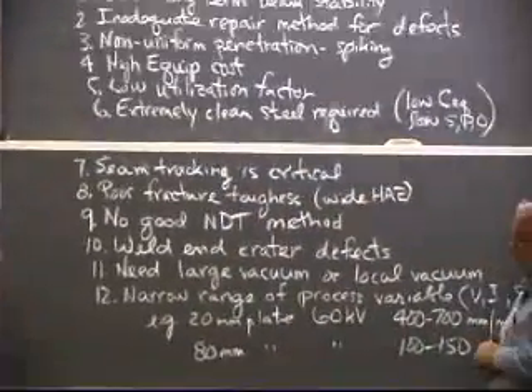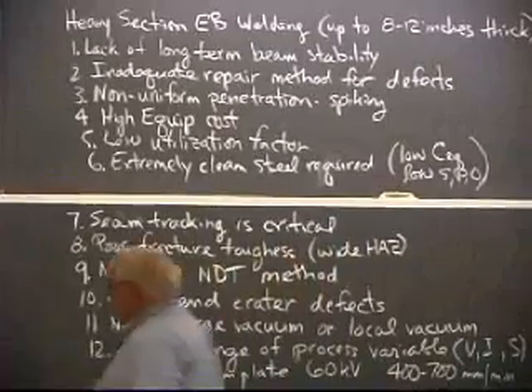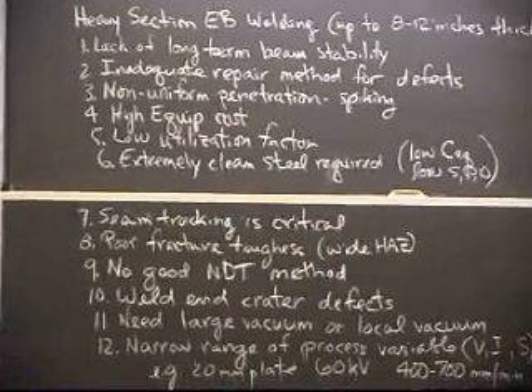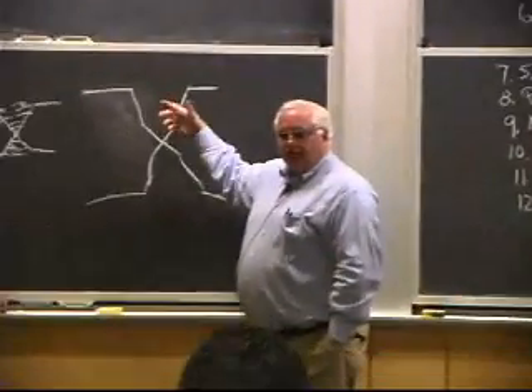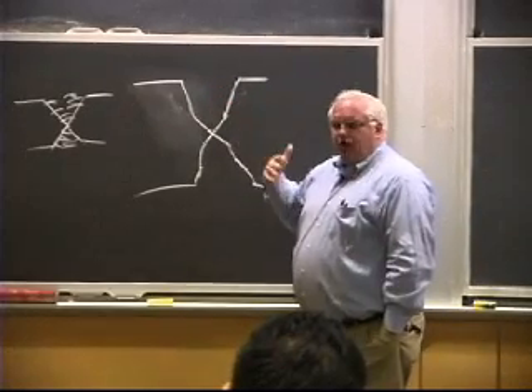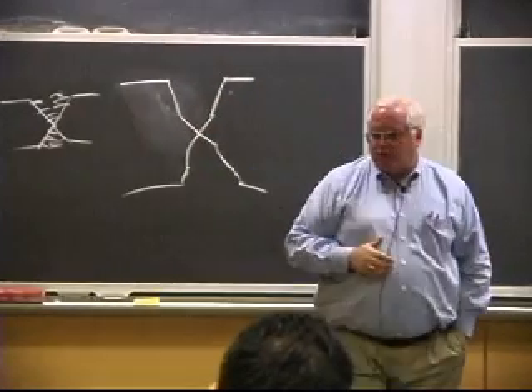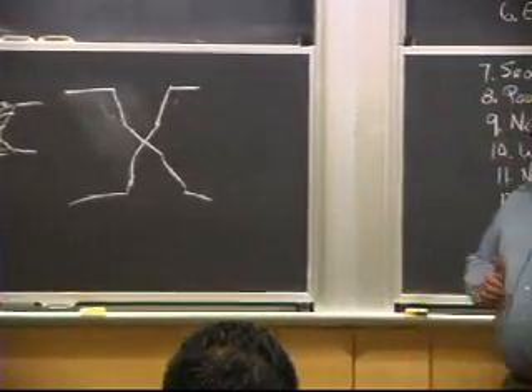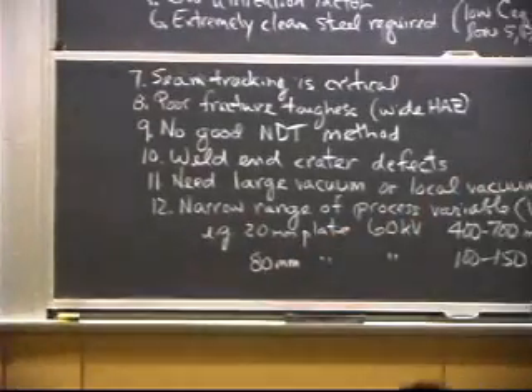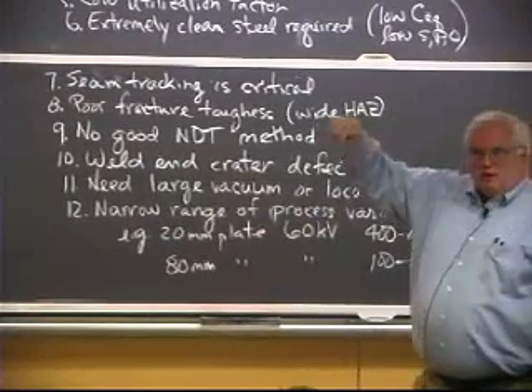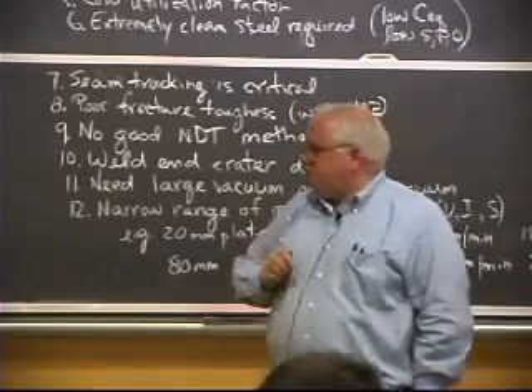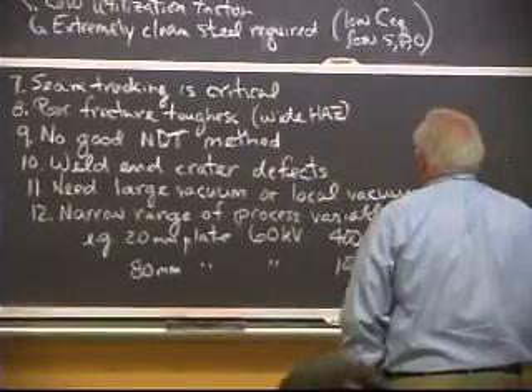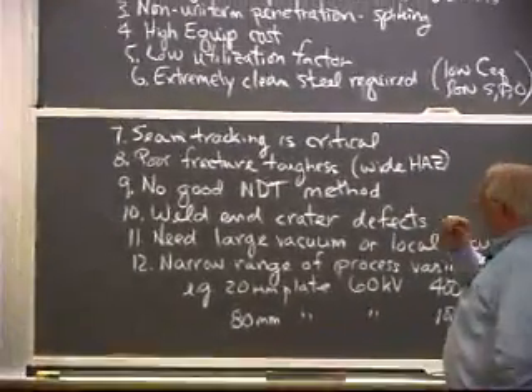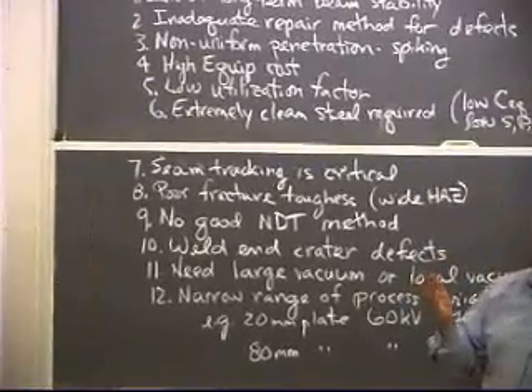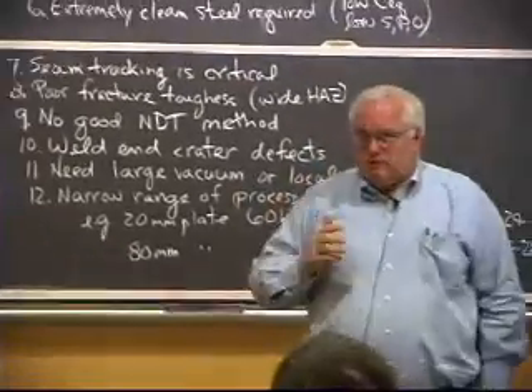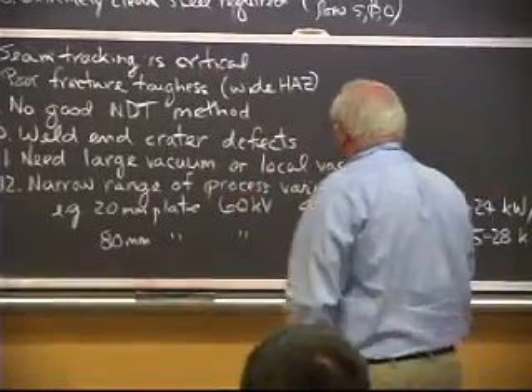Inadequate repair method of defects. Well, if I've got something that's 8 inches thick, and I have a flaw down here in the middle, I've got to dig that whole thing out. And if I dig it out, what am I going to do? Manual repair? I can do a manual repair, but what about my residual stresses when I'm all done? Okay? It'd be horrible to have to repair that. Non-uniform penetration, you saw that in the movie, the spiking that you get. That's kind of inherent in the process. High equipment cost. The research machines were about $2 million a piece, and there were probably a dozen of them in Japan, in different research labs.